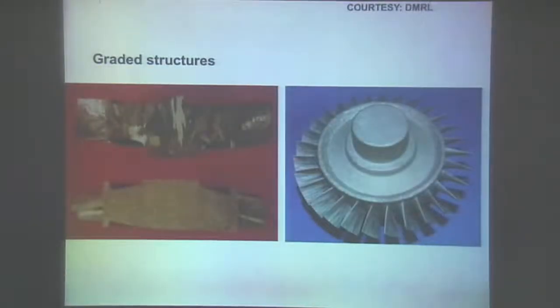What are the solutions to these emerging limits of material performance? One way of looking at solutions is to look at graded structures. So here's an example of a graded structure engineered at DMRL, and this is an integral rotor part made of nickel-based superalloy. If you conventionally cast the material, you get large coarse grains which look like this, which is terrible for fatigue resistance in the bore of the disc. If you vibrate the shell during the process of solidification, you create large numbers of nuclei for solidification, and you can transit from those coarse grain structures to very fine grain structures. But of course, the grains are fine even in the blade portions of this material where you require creep, and that's not so good for you.